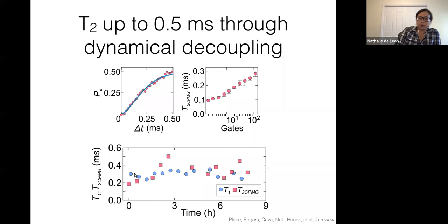Just to show you that we're not cherry picking the data, one of the things that's often hidden under the hood of these experiments is that there are actually variations in time for T1 and T2 of these qubits. So here's a time sequence where the T1 is relatively stable around 300 to 400 microseconds, and the T2 varies a little bit more, but it's still comfortably always over 200 microseconds.